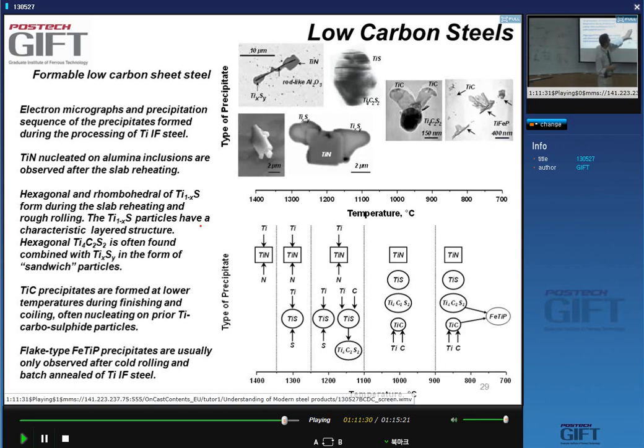Next thing that happens is, as you go in the hot strip mill, from high temperatures, somewhere around 1300, down to the austenite-ferrite transformation, and then you coil the material, and it cools down very slowly to room temperature. As the temperature decreases, the next things that form are sulfides, in the IF steels the sulfides of titanium.